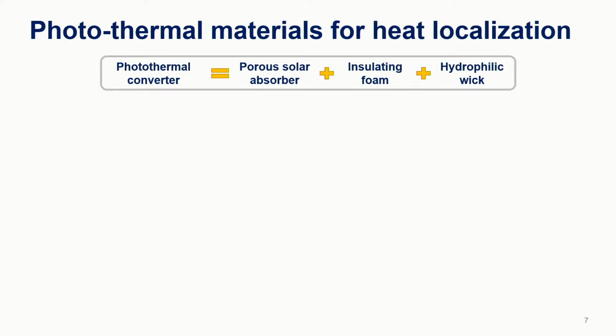And again, this is where we can use materials, specifically photothermal materials. So as the name suggests, you're converting those photons into thermal energy or heat, and you're localizing the heat at the surface, because evaporation is only a surface phenomenon. So if we can localize all the heat at the surface, we'll increase the surface temperatures, and that'll increase our evaporation rates.